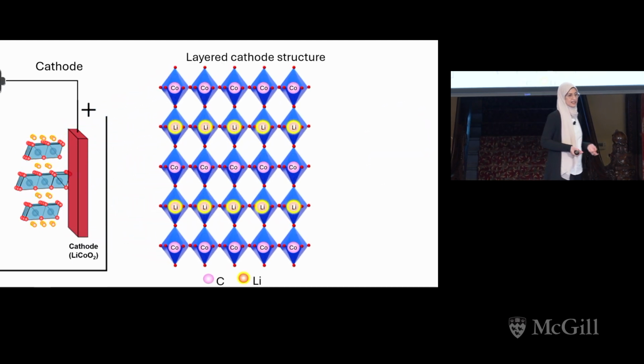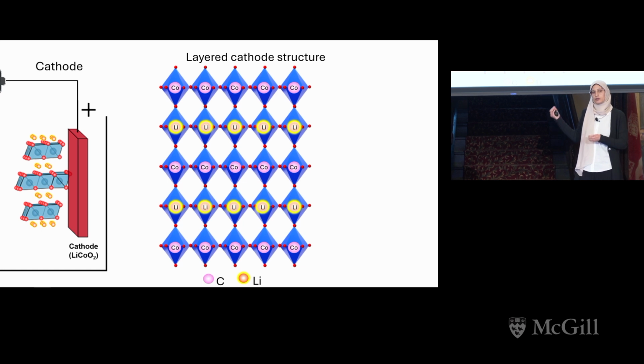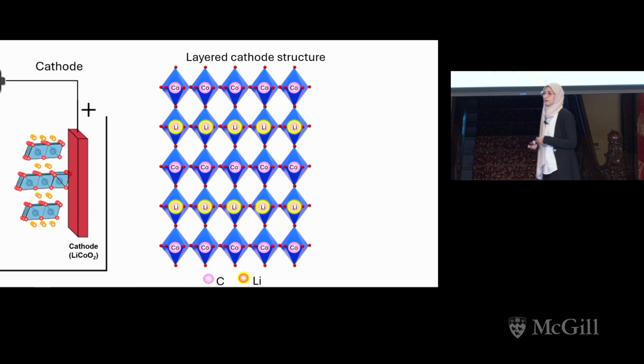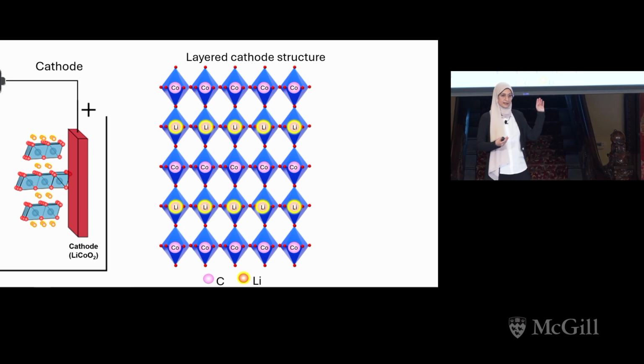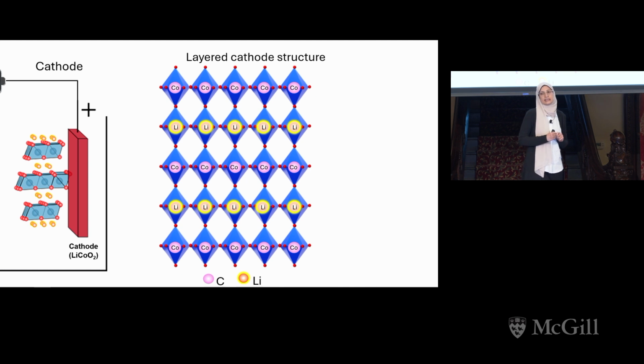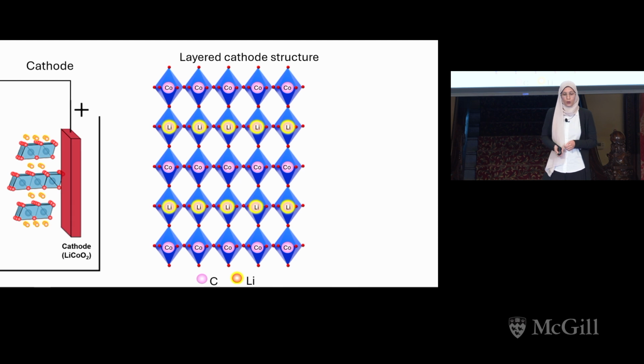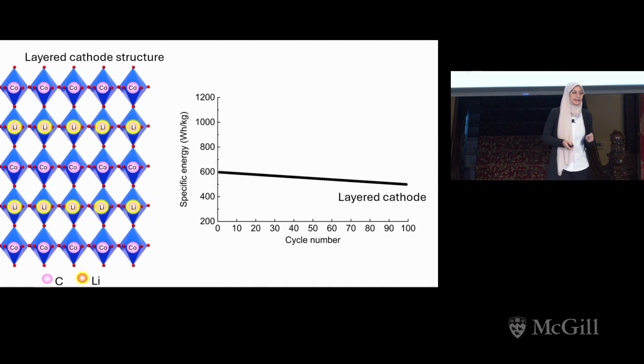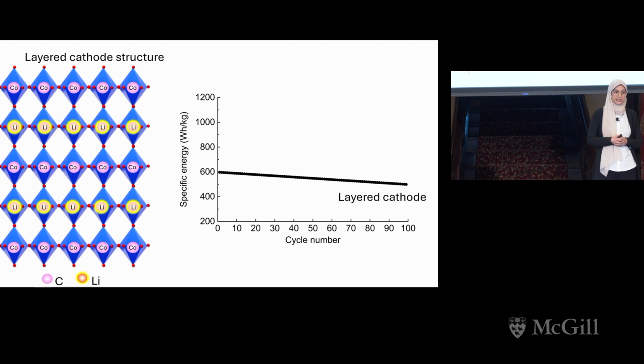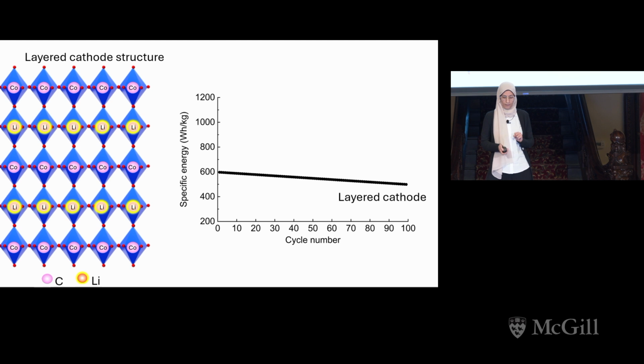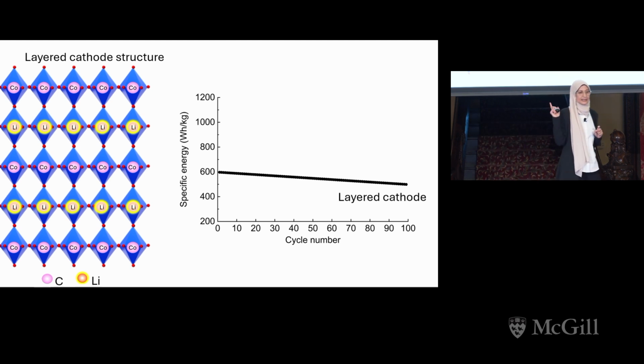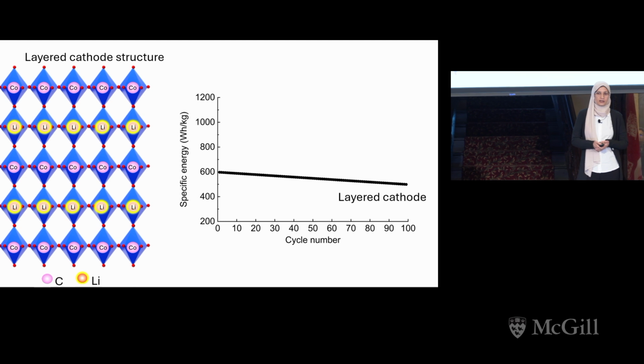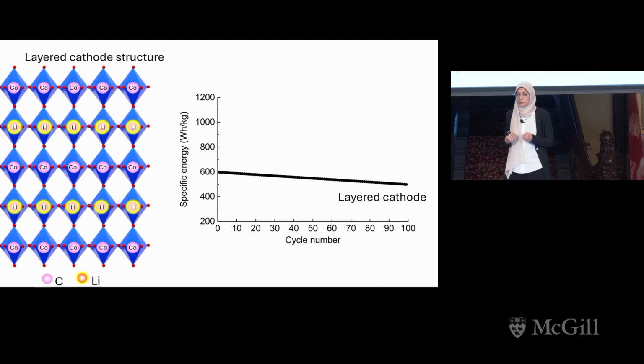Let me show you one of the most commercialized cathode materials. This cathode material has a layered structure. For simplicity, I'm just giving you a simple example, which is lithium cobalt oxide. In the layered material, lithium and transition metal, which is cobalt in our case, are arranged in alternating layers, which means we have lithium, cobalt, and so on. With this layered material, we can get around 600 watt-hour per kilogram energy density. Watt-hour per kilogram is how we measure the energy density. This material will be our reference point for today's presentation, which means I will compare my material's performance later with this material.